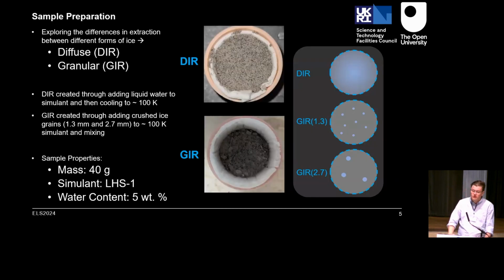So for this work, I wanted to look at the different forms of ice. We don't really know what the true composition of the ice at the poles is. So I looked into building the two, I would say, most straightforward forms of icy regolith you can make. The first one would be diffuse ice, where you essentially add liquid water to room temperature simulant, just mix it as well as you can, and then you cool it down to 100 Kelvin with our setup.